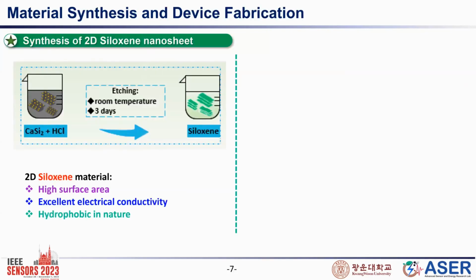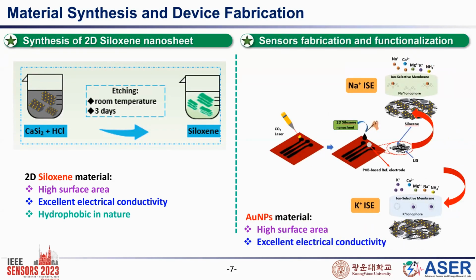This shows the schematic of the synthesis of 2D-Siloxene. CaSi2 and HCl, it's an etching process that takes 3 days, a long time. This is the calcium part. Then it forms thin double layers, a multi-layer structure of 2D-Siloxene. And this shows the fabrication technique of our epidermal patch. There are 3 electrodes: one reference and 2 working. One working is the sodium ion sensor and another is the potassium ion sensor. We have functionalized these and used the ISM, ion selective membrane, using a sodium ionophore as well as valinomycin for the sodium and potassium ion sensors respectively.